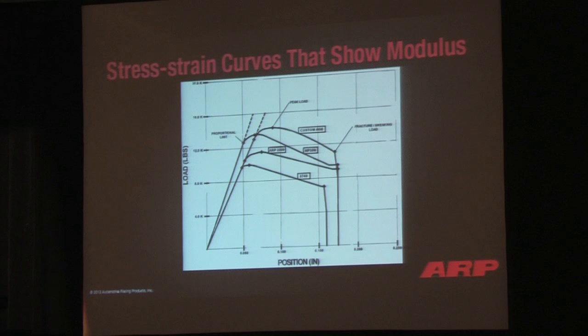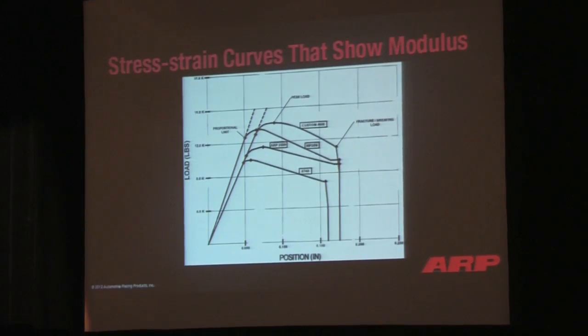The exception to the rule here, which also demonstrates the modulus, is this material here, which is MP35N. This has a modulus of elasticity that's about 12% higher than the other 3 materials. So again, the rate at which it stretches is different. So this particular material is stiffer. But all these other materials, the rate at which they stretch is the same. All you're doing is raising the yield strength. Just by having a higher yield strength doesn't make it more resistant to stretch.